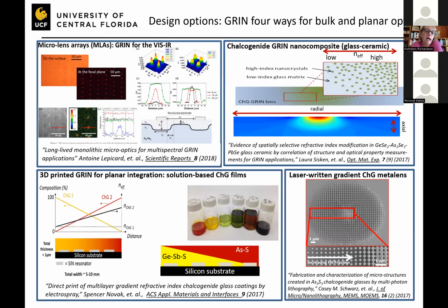So we've worked a lot on GRIN over the course of the last decade. I'm not going to go into a lot of details. We've done it in making glass ceramics. I'll talk about that a little bit more. We've been working with our colleagues at Bordeaux, where we have been able to use thermal poling to change not only the composition and therefore the refractive index. If we can change the index in a spatially controlled way, we can change the shape of these lenslets so that we can make micro lens arrays, for example, both in the visible and the infrared.